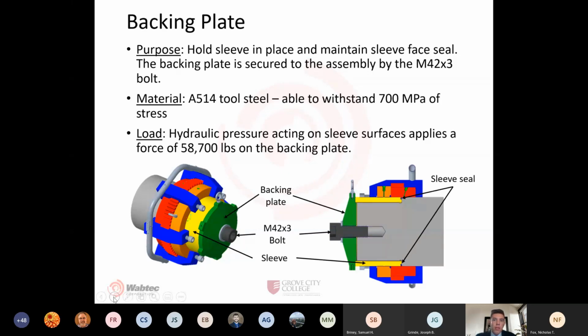The backing plate is made from A514 tool steel that has a yield strength of 700 megapascals. A force of 58,700 pounds is applied to the backing plate during the removal process. And this force is the result of the hydraulic pressure acting on those sleeve surfaces that are above the seal. Next slide.